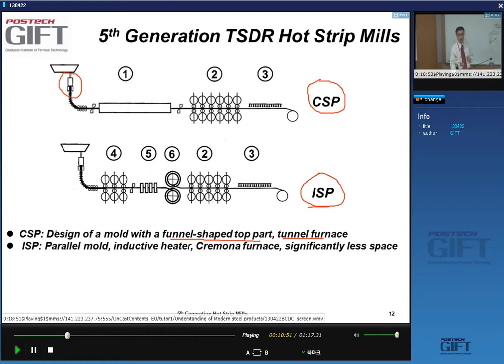In the case of this ISP, we don't have this funnel shape, we have a parallel mold. The reason is we're actually casting a thicker strip, yeah, and we are rough rolling this thicker strip. Compensating for the heat losses and getting a homogeneous temperature distribution in the bar is achieved in a tunnel furnace, a very long furnace. Here it's achieved by induction heaters. So you basically reheat the bar.